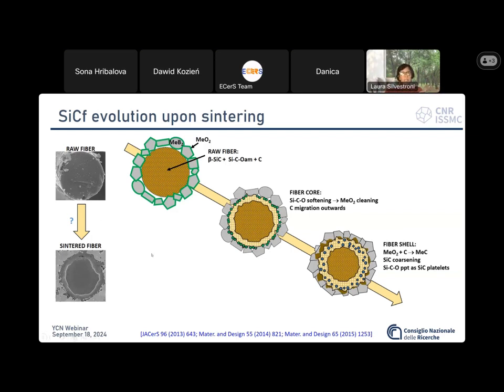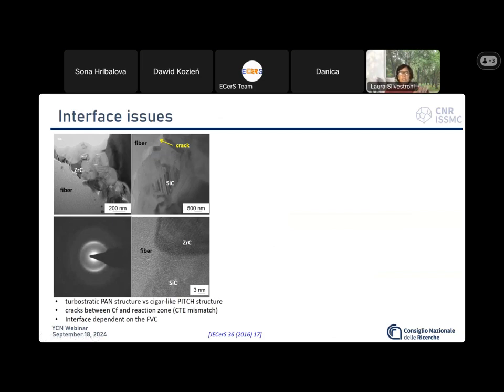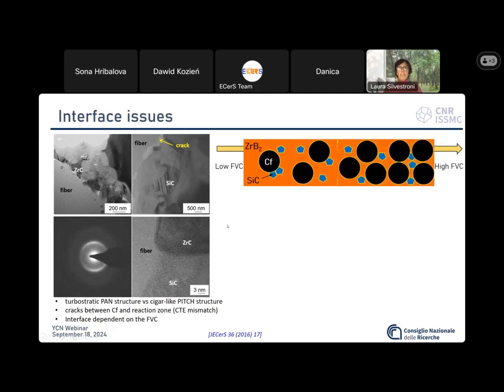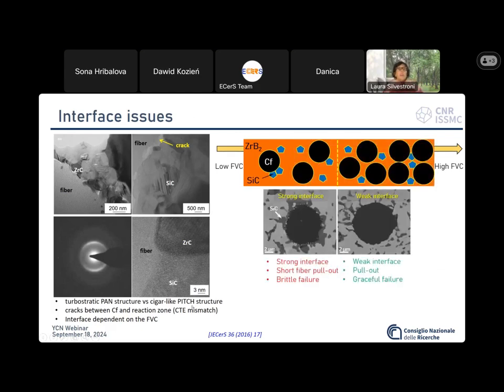A similar trend is observed, of course, also on the carbon fibers, where the extent of the interaction is defined by the production process of the raw fibers. That is, it depends if they derive from PAN-based or pitch-based. Furthermore, beside this general interaction, we have noticed that beside the additive, the strength of the interface domain between fiber and matrix varies depending on the fiber volume fraction. We have stronger interaction for low fiber content and weaker interaction for high fiber content.